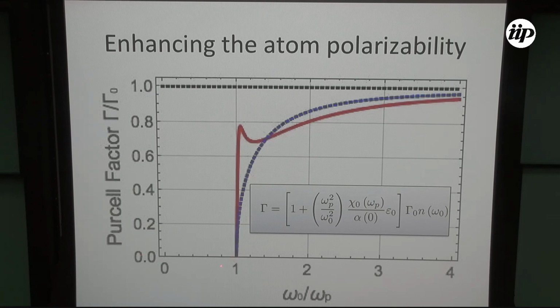So it depends on where you place the emitter energy. If you place the emitter energy to the left of number 1 here, it's reflective, doesn't transmit, and you don't have spontaneous emission. If you place it to the right, if it were not for the renormalization of the polarizability, we would have a very small emission rate, here is the blue line, very close to 1. We would have a very small spontaneous emission rate, but because of this resonance, you can have a very high emission rate. It still is lower than the vacuum, but this can be considered a Purcell effect, because the red line is above the blue line. So it's a Purcell effect inside the medium.